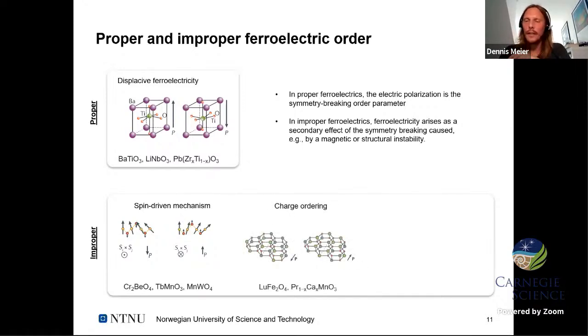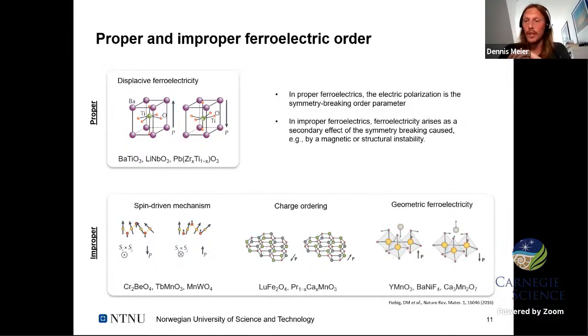A second one is charge ordering. What's happening here is that we have alternating layers of ions in a different valence state. For example, in the case of lutetium ferrite, iron 3+ and iron 2+, so that we end up with an imbalance and alternating layers with a spontaneous polarization in between. This mechanism is one that is still discussed a little controversially, so I will not go too much into that direction. I will rather focus on the third one, geometric ferroelectricity, where we have a geometric transition, for example, in the hexagonal manganites, where manganese-oxygen octahedra buckle and tilt, and then lead to a polar displacement of the atoms, causing ferroelectricity. Let's discuss that in a little more detail so that we are all on the same page and you see why I'm so interested in these materials.